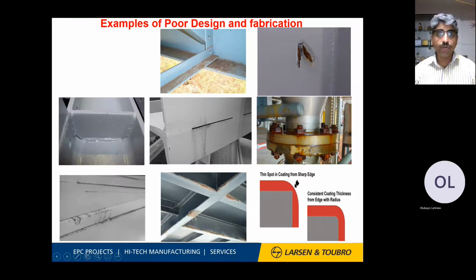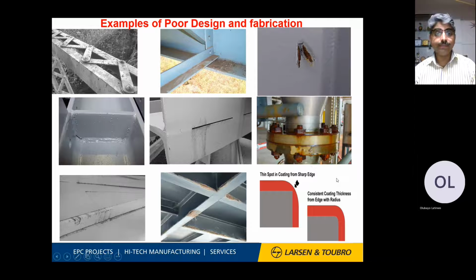So small things, if you address in terms of design, you will enhance the life of the component. Here you don't do any miracle, but only you have to make a 3 degree taper for the corner joints. It is going to kill your premature failure of equipment. This is another example where we say that there are riveted joints. Riveted joints always form crevices, and because of that, they get much faster corrosion than what we think. So nowadays, this is replaced with welded joints.